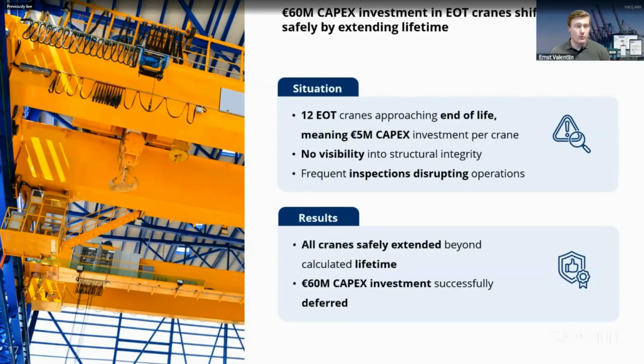So in response, they thought, if we have to continuously monitor that and do very frequent inspections, due to how hard these locations are to access, that is not a business case we can make. That is difficult for us. It might be better to then do the investment. At that point, they estimated about 5 million per crane to be replaced. Or we can start inspecting these locations at a slightly lower frequency and monitor them in the meantime to make sure that these cracks are not starting to happen there.